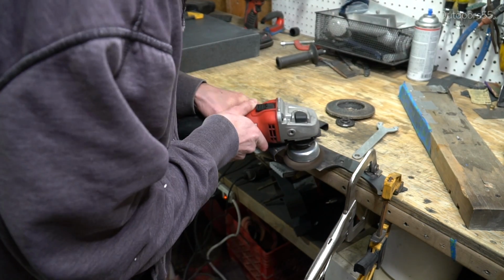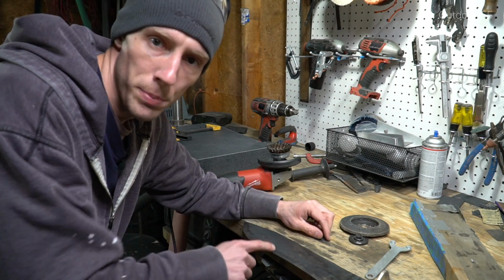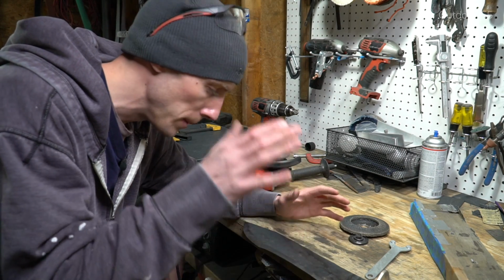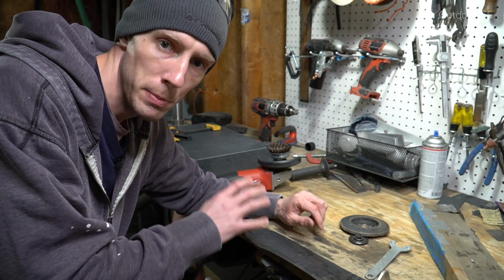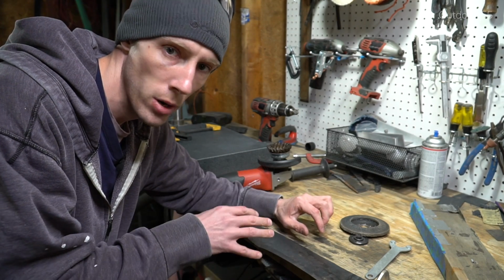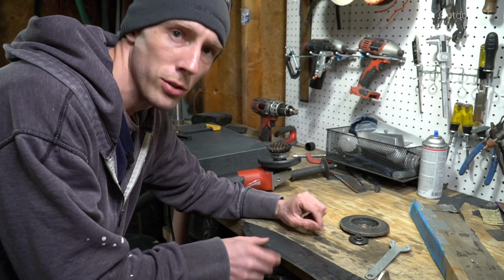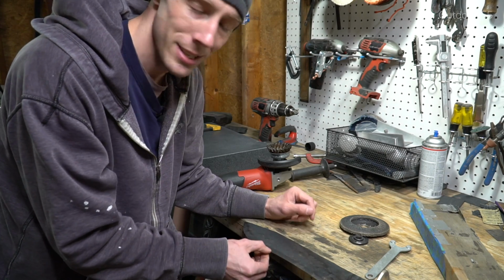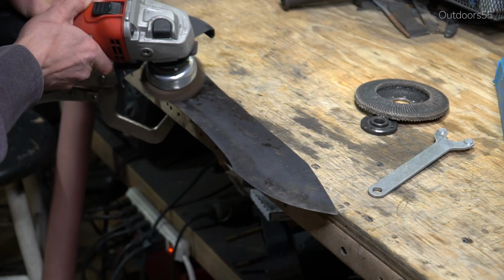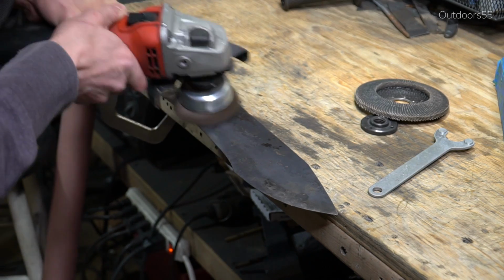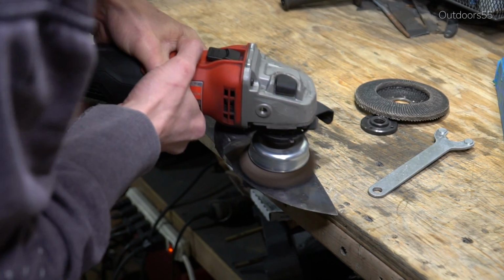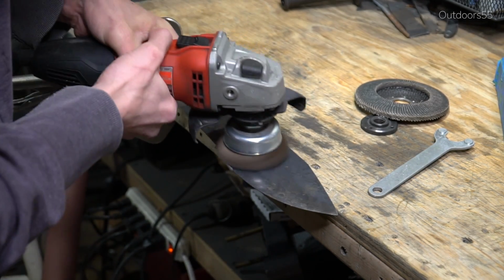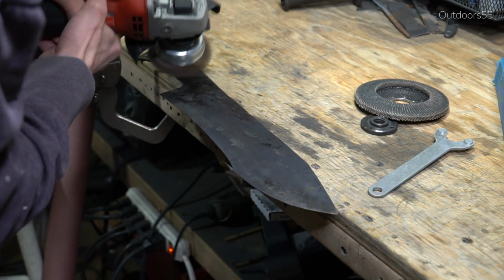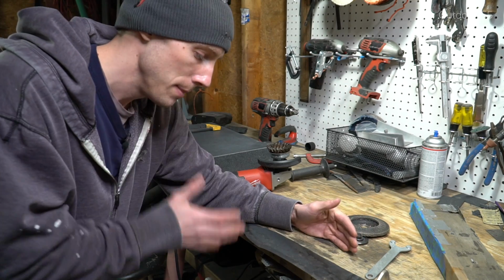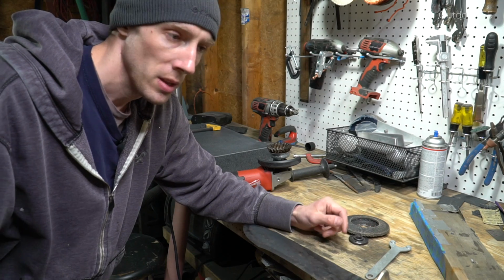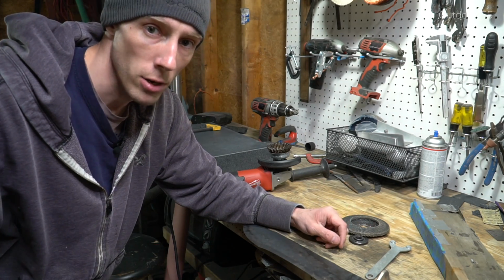I should mention here real quick that you want to take super extra careful precautions about not overheating this blade. You do not want to get it over 400 degrees. Now the super thin edge here, this can overheat in seconds with an angle grinder. So dip it in water often. You can keep a spray bottle full of water next to you and just kind of spray it off. Whatever you have to do, go out of your way 100 times over to keep this blade cool, because if you overheat it, you basically ruined it and you got to start over.